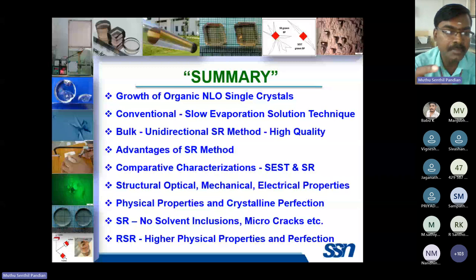So only very high efficient materials we have selected and grown by this SR method. We mount the seed crystal at the bottom of the glass sample. We pour the solution into the SR method glass sample and we grow large size crystal by this SR method. But still a lot of impurities are segregated in this conventional SR method, which we have to avoid when we grow the crystal for nonlinear optical application.